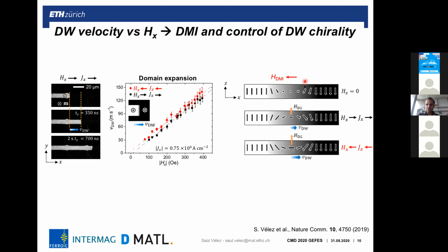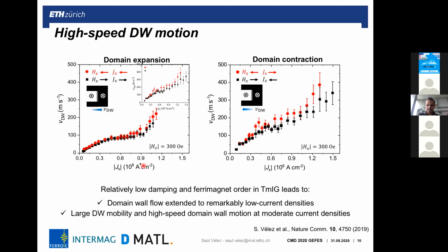So here I'm showing the domain wall structure that we expect. We have a partial Néel chirality because of the internal DMI in the system. Now when we set the magnetic field, we either help the domain wall to be stabilized or we set the chirality to oppose the original one because of the DMI. That's why we observe this shift. So from this we can measure the DMI, and we can say that we can control the domain wall propagation by controlling the direction of the current, of the magnetic field, and the DMI in the heterostructure.